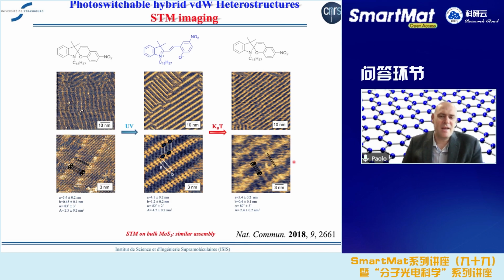And then STM can be done in situ. Of course, preparing films that are highly ordered at the solid interface is easier than in dry films. There you have to control a bit more the concentration. But Marco Gobbi showed that this is actually very well possible. There are many other papers about dry films studied by STM that you can find in the literature. So that I think is doable, and it's very important because this kind of STM imaging allows you to correlate the very structure at the atomic level that you have in your, let's say, superlattice with electrical performance that you have studied in the transistor type of device.